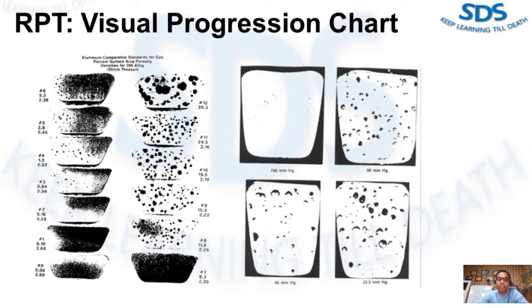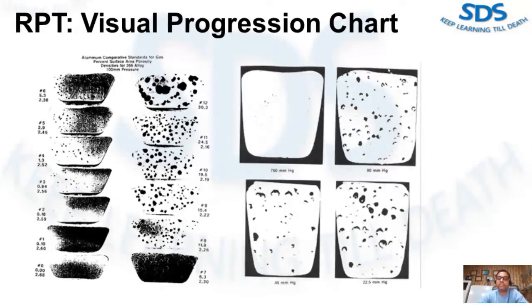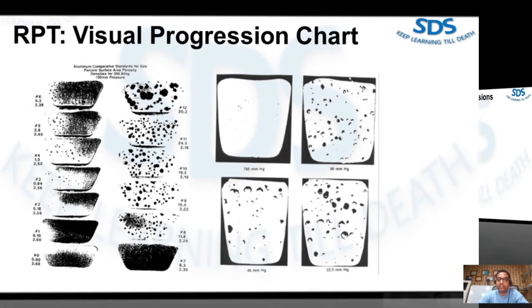The density of the reduced pressure test sample can also be determined and used as a measure of porosity. However, the reduced pressure test does not determine hydrogen directly — it is rather a measure of melt cleanness, as the presence of inclusions will nucleate porosity during the test. Therefore, the reduced pressure test is actually a measure of general melt cleanness and not hydrogen content specifically.